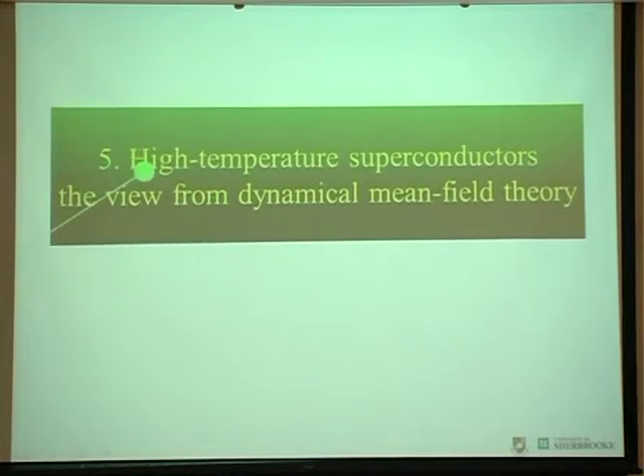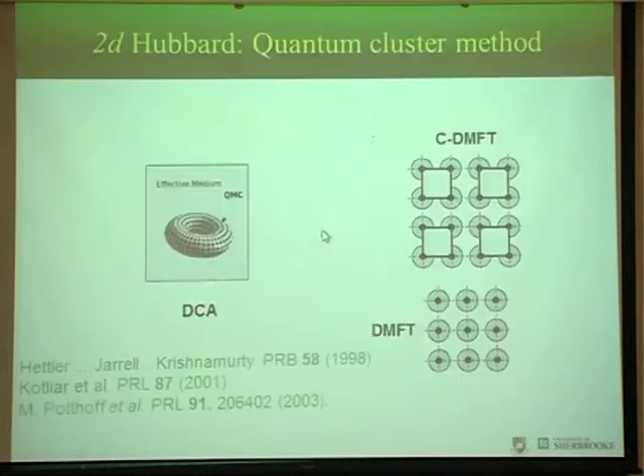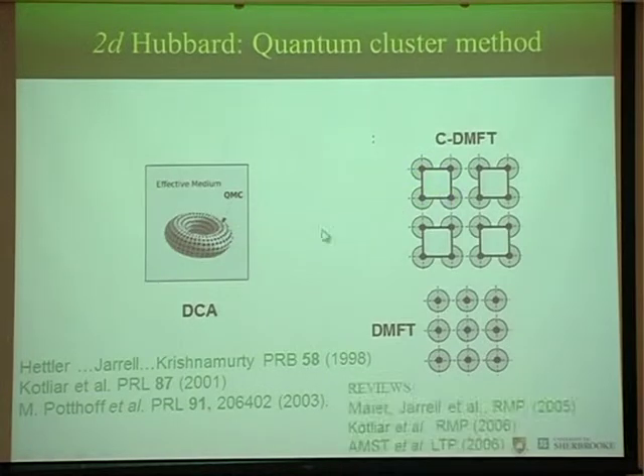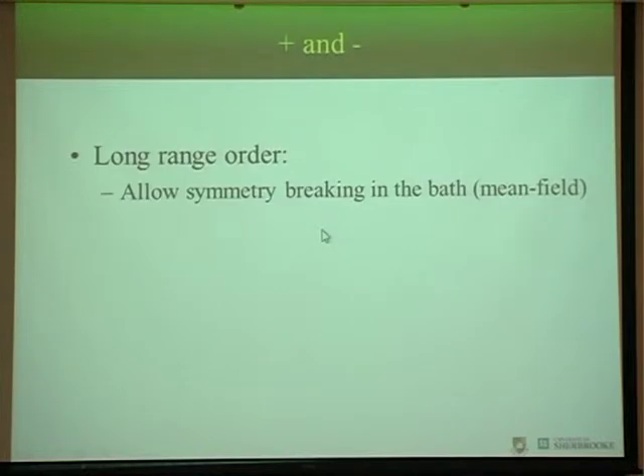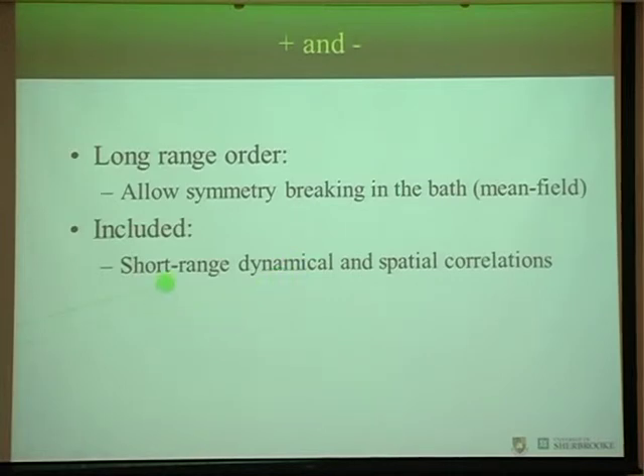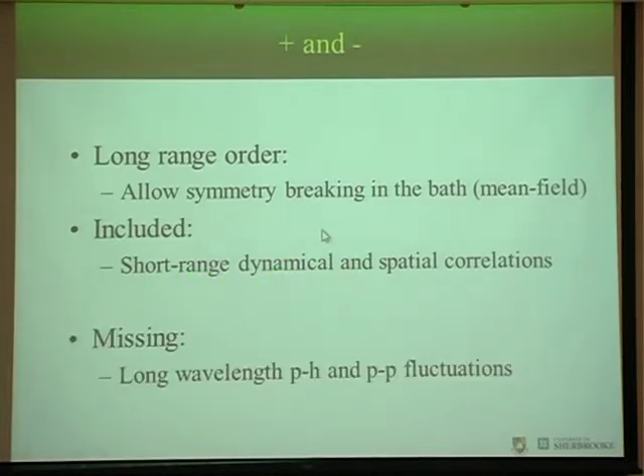So, okay, now high temperature superconductors, the view from dynamical mean field theory. So we do these cluster calculations that I mentioned in one of the first transparencies. And there are many calculations by Andy Millis's group also using DCA, and Mark Jarrell's group, and some collaborators here in India. So among the many positive aspects of these dynamical mean field calculations is that long-range order is not done in any mean field way on the cluster. You just assume symmetry breaking in the bath, and you see if it is self-consistent. What's included is short-range dynamical and spatial correlations. And what is not included is the long wavelength particle-hole and particle-particle fluctuations.